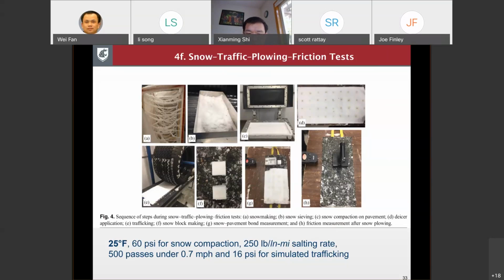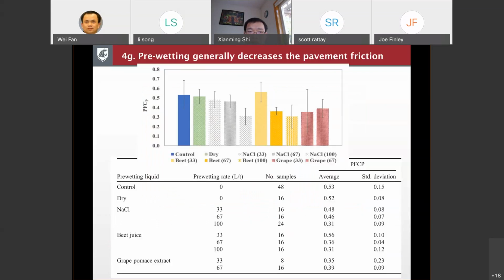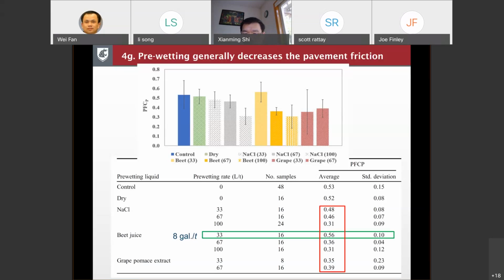And then we start testing the bond strength and friction coefficient on the pavement afterwards. One thing is that the pre-wetting generally decreased the pavement friction, which is a surprise to us, of course. The only good news is that for the beet juice blend, at a low application rate, 8 gallons per ton, we're seeing dramatically improved friction, much more so than the control. But in most other cases, we are looking at lower numbers, which is undesirable.